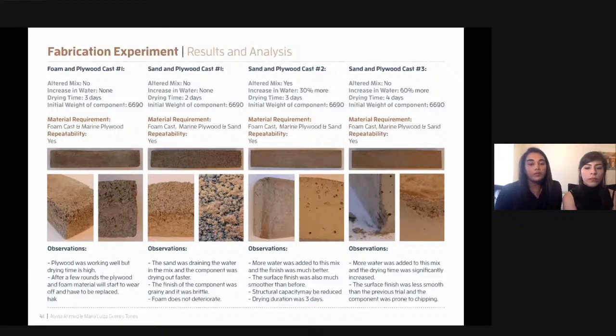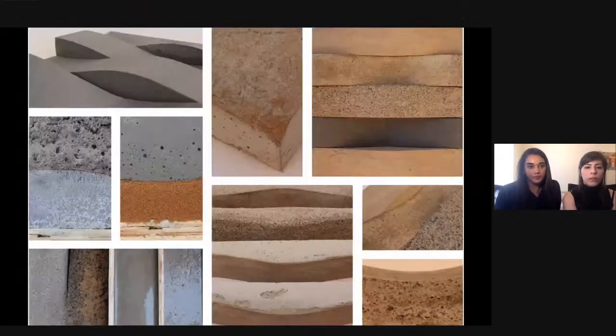However, the components were more prone to chipping and breakage. Both techniques performed well in terms of their respective materials used. Foam casting with plywood was used as a guide test, and we observed that the repeatability would be reduced due to their water permeability and deterioration in the foam and the plywood.